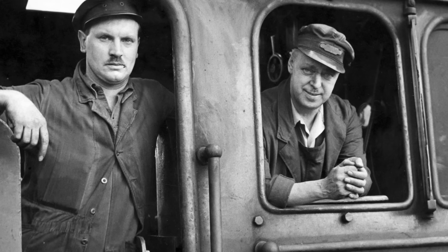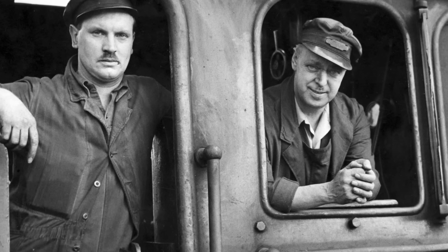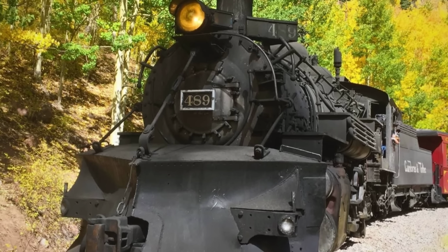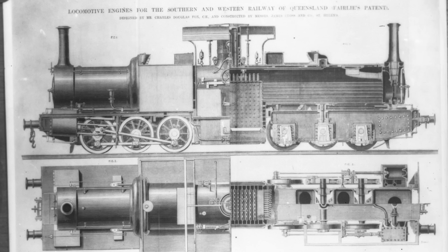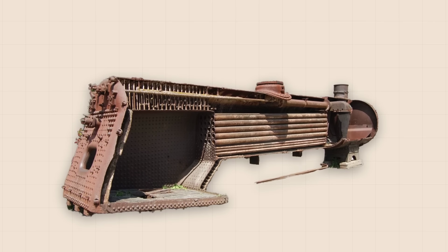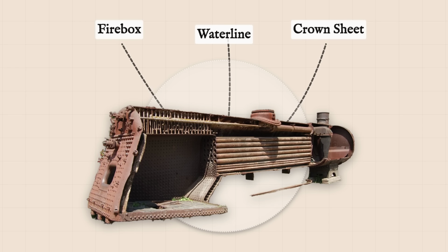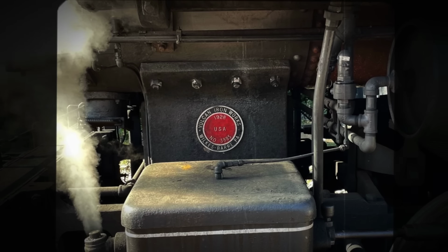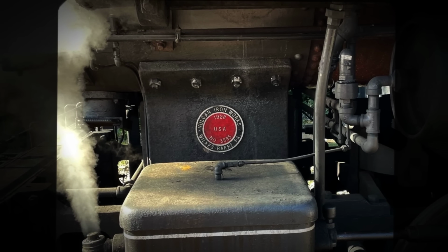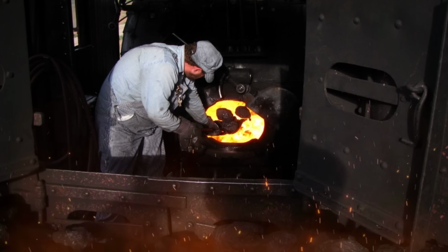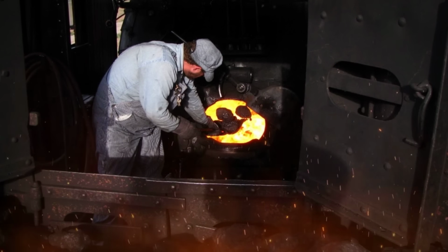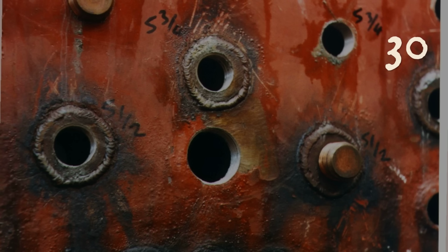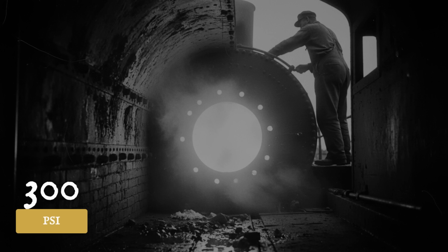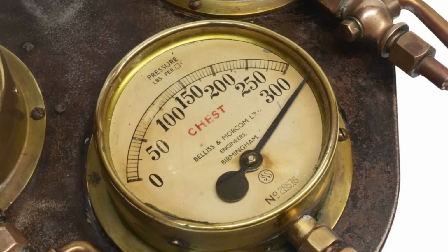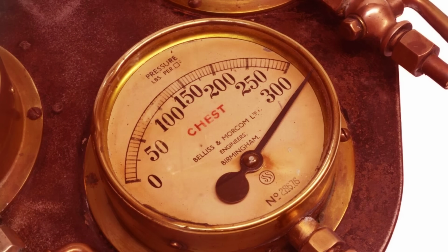Water is the shield and the saboteur. In the closed system of a locomotive boiler, its behavior is never neutral. On a steep grade, tonnage drags the engine uphill, and the waterline tilts. Gravity pulls the liquid forward, uncovering the rear edge of the crown sheet in seconds. That half-inch of steel, no longer cooled by water, absorbs the full heat of the firebox, over 2,000 degrees. Within half a minute, the steel softens, losing more than half its strength. At 1,200 degrees Fahrenheit, it surrenders, and the pressure inside finds the new weak point.